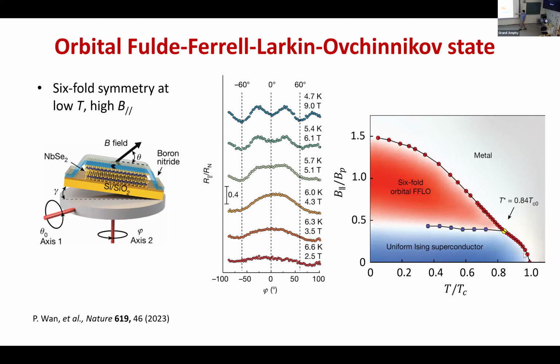So basically what they're doing is they measure how the upper critical field responds to your in-plane field. And if you're here, then it's isotropic. And if you're here, then it shows you some kind of six-fold symmetry. So they argue that these features are somehow consistent with the expectation for orbital FFLO state.